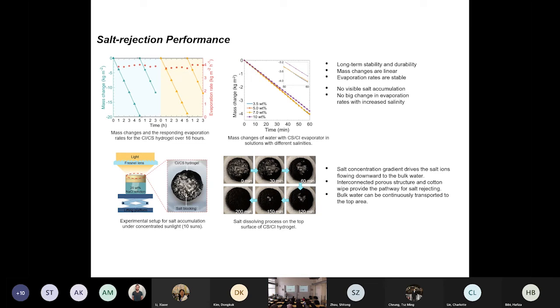So we demonstrated, for all of those materials that we studied so far, the salt rejection performance. So as you can imagine, under 10 suns, clearly we can see all of that salt sits on top of the surface. It's going to block the pores. But the problem is we're not able to use this system 24 hours a day. We let this material float at the water interface under solar exposure only for the daytime, no more than 8 hours a day, 6 to 8 hours a day.